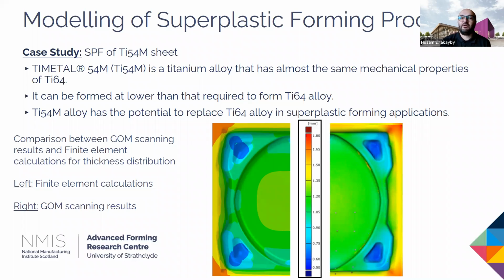You can see in the figures the thickness distribution of a component after being formed. On the right side is the GOM scanning result of the formed component, while on the left side is the finite element calculation. There's a good agreement between the FE result and the GOM result. This is one outcome we have from the analysis.